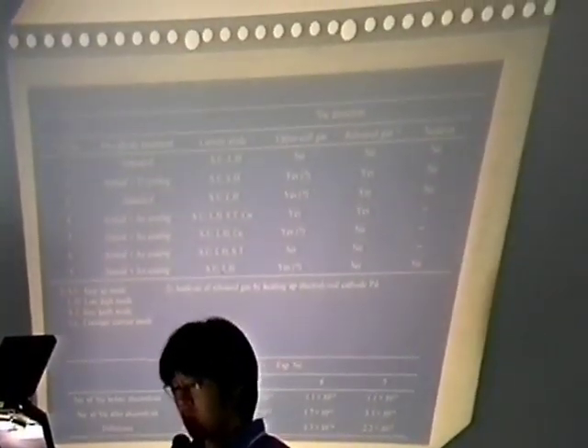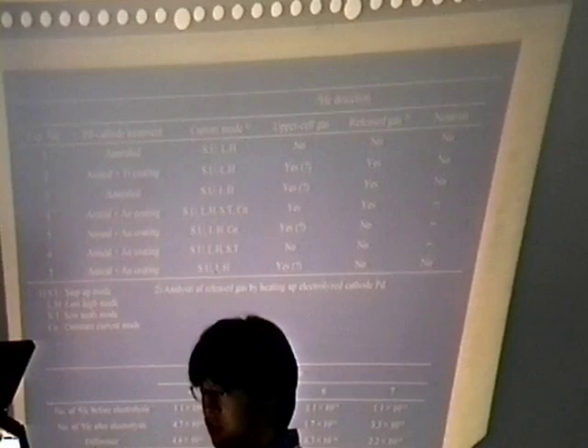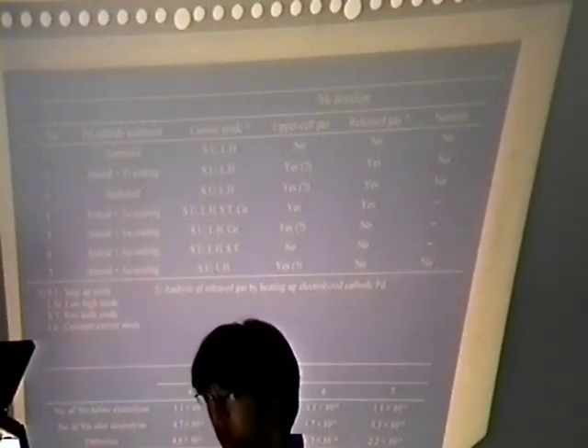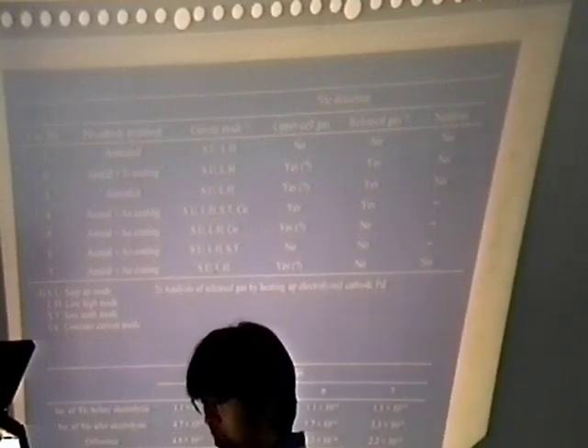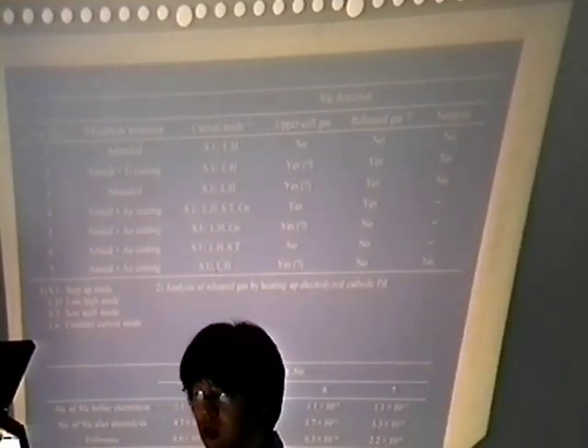I show the summary of the experimental results. Totally, we performed 7 runs, and the palladium cathode used in this experiment was treated like this, annealing or metal coating. In 3 out of 7 runs, we can detect helium-4. Especially in EXP4, we can detect the helium-4 so clearly.